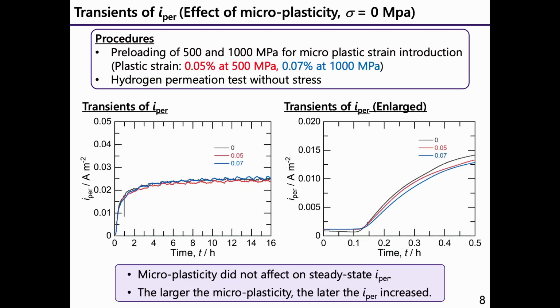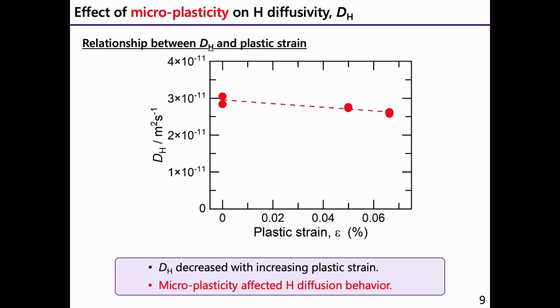Here is a transient of hydrogen permeation current. From the left graph, microplasticity did not affect the steady-state hydrogen permeation current. On the other hand, the right graph shows the enlarged one with the initial half hour. You can see that the larger the microplasticity, the later the hydrogen permeation increase. Based on the hydrogen permeation current measurement, we calculated the hydrogen diffusivity, and the relationship between hydrogen diffusivity and plastic strain is shown here. Hydrogen diffusivity decreased with increasing microplastic strain. It means that microplasticity affected hydrogen diffusion behavior.